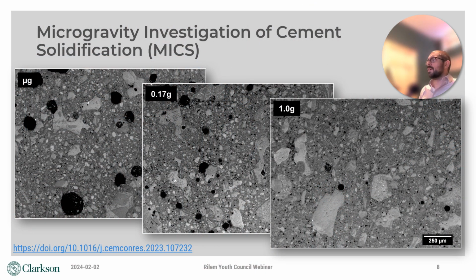They were kind enough to share some of those samples with us so we could study their microstructures and properties. And here you see 3 Portland cement samples with lunar simulant aggregates that were hydrated at microgravity, lunar gravity, and Earth gravity. One of the most obvious changes we see is the appearance of coarse air voids in the space-hydrated samples. It turns out that gravity is extremely helpful in consolidating the fresh concrete.